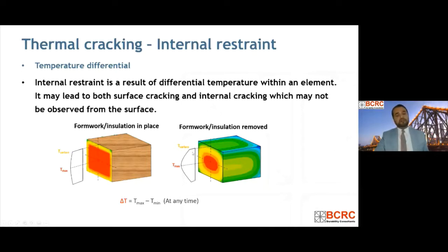So our temperature differential is basically the maximum temperature minus the minimum temperature at any stage during this process. It's not just when the formwork is in place. It can happen once you remove the formwork, so that temperature differential should be considered at any stage during this whole process. Now we know what the temperature differential is, so we can see how this internal restraint or temperature differential causes the cracking.